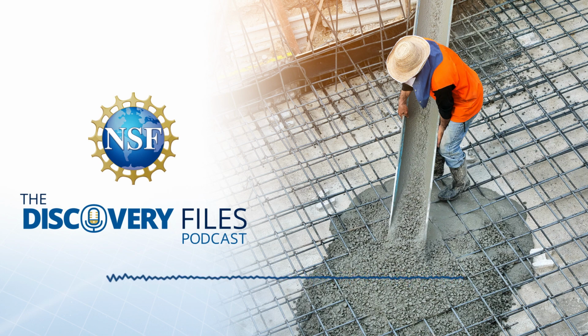And then we also looked at high temperature exposure, which was just putting them in a furnace for an hour at 600 Celsius. We talked to some people at Kennedy Space Center, and they let us know that one of the things that will be most important to build are these takeoff and landing pads for the rockets to protect them from debris. And so if these materials are being used for that application, they might be subject to very high temperature. And so we weren't able to mimic exactly a rocket taking off.